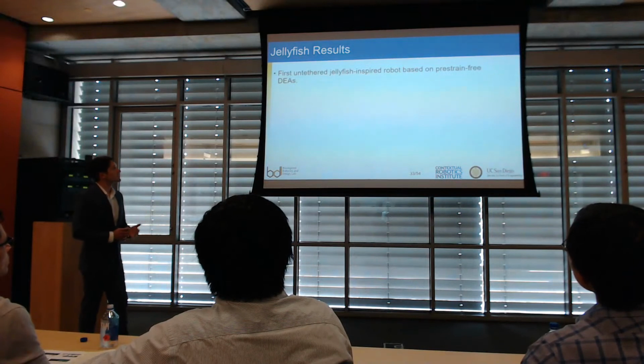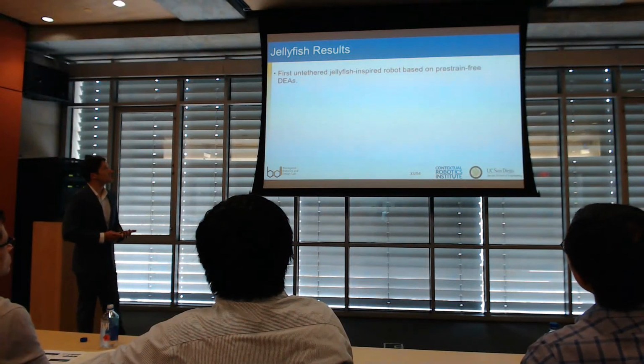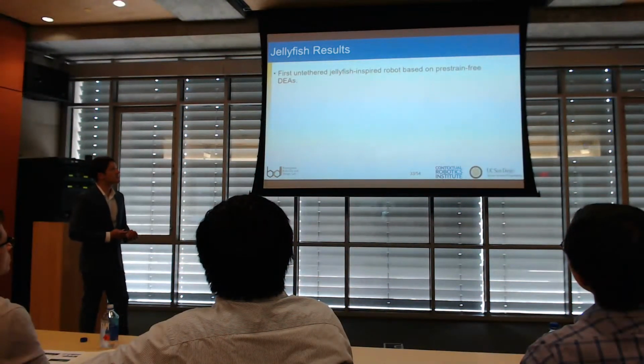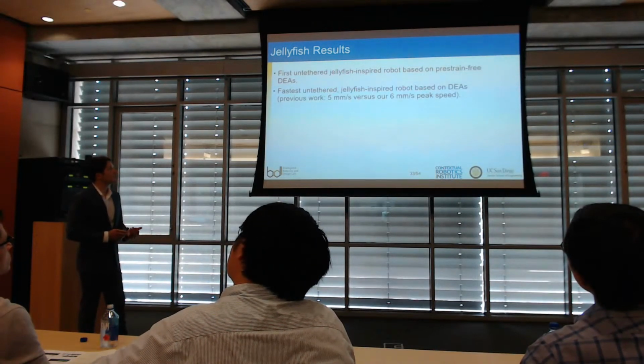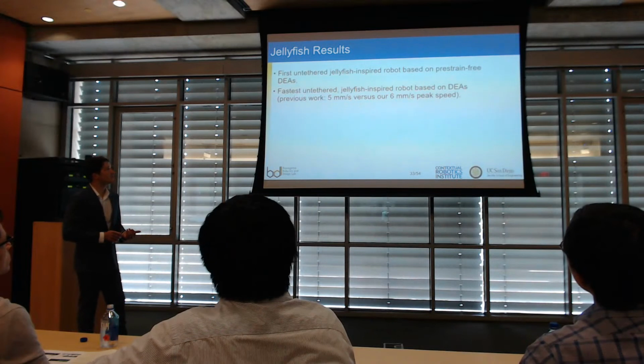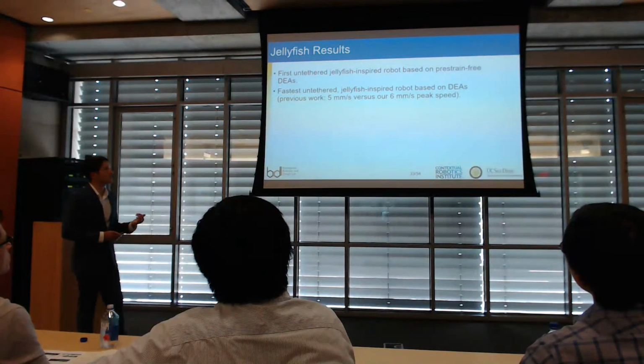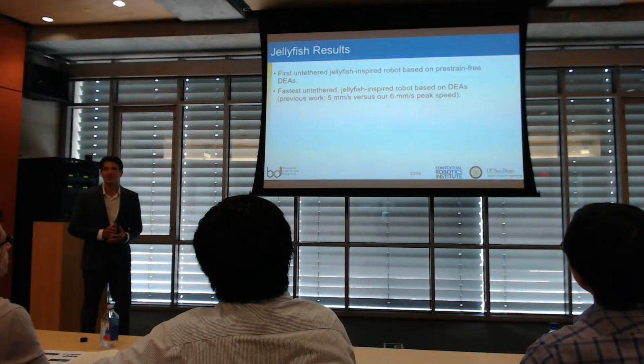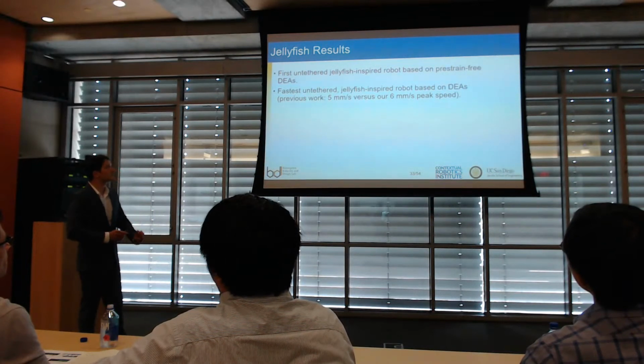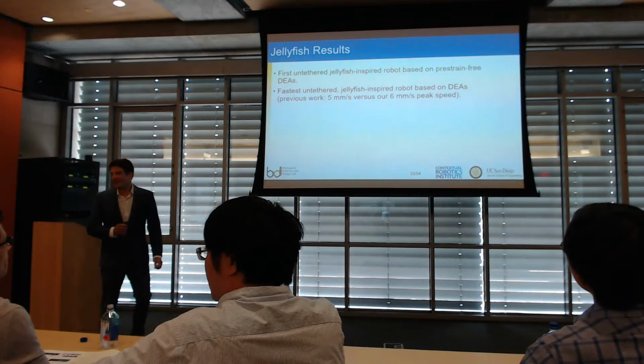So for the results of the jellyfish, this is the first untethered jellyfish-inspired robot that's based on prestrain-free DEAs. And then also it's the fastest untethered jellyfish-inspired robot based on DEAs. The last record was 5 millimeters per second, and then ours is a little bit faster, about 6 millimeters per second. So it's not a big improvement, but I'll take it.